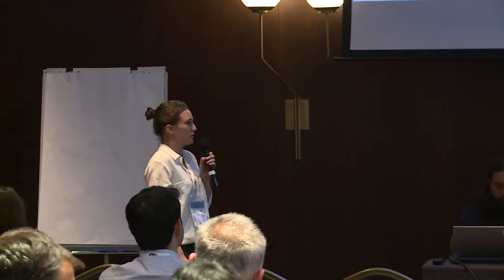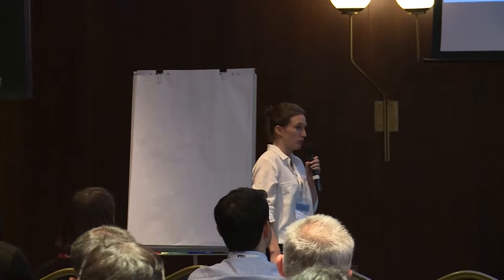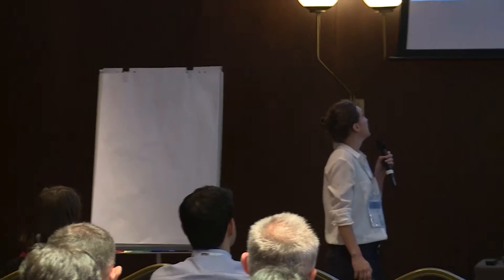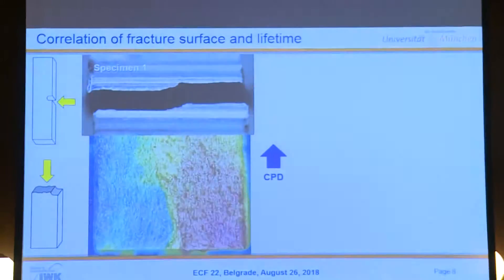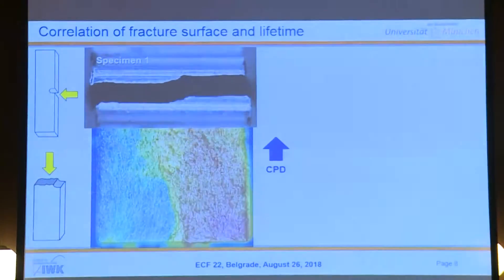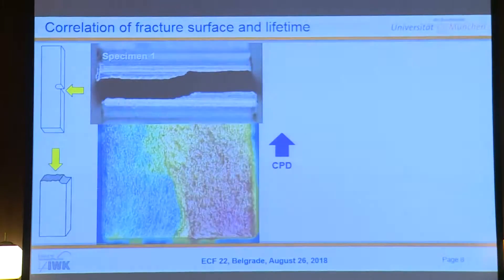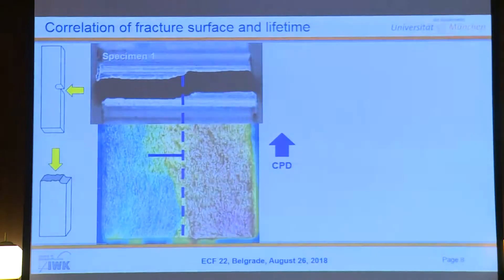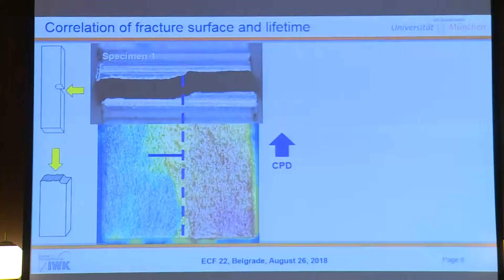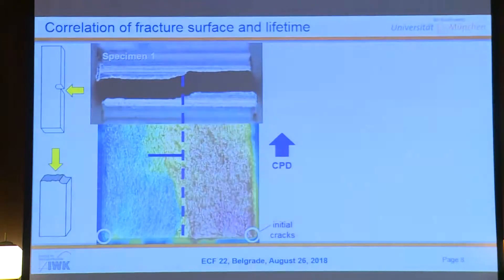Now, how can we correlate this with the fracture surface? We look inside the broken notch and see where the crack broke. We can also look at the fracture surface — this is a 3D topographic picture. The notch is at the bottom and the crack propagation direction is along the arrow. What we can see is a so-called step. We observe it on both pictures; this step has a certain length and a certain height. Later I will discuss the point of coalescence — the point at the end of the step when the initial cracks grow together. We can combine this with the position and amount of initial cracks visible under the electron microscope. In this case, we have two initial cracks right at the edges of the specimen.